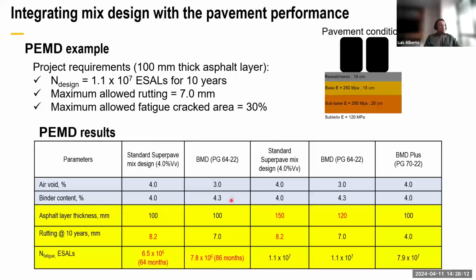So for the Superpave mix design, in order to attend the project service life, we need to increase the asphalt layer thickness from 100 millimeters to 150, and for the optimized mixtures, only 120 millimeters was enough to achieve the target.